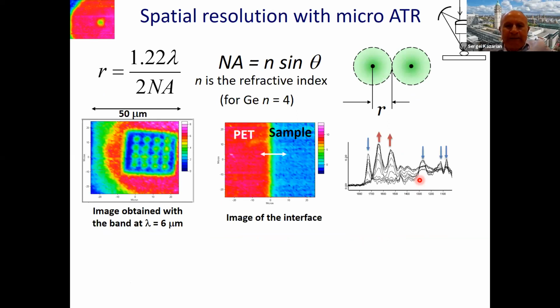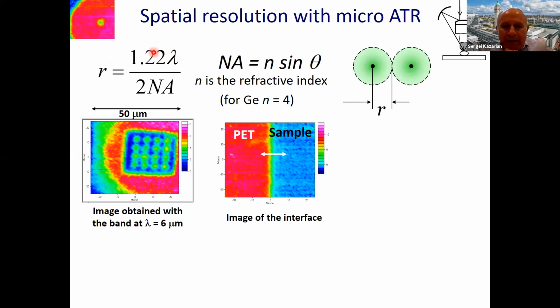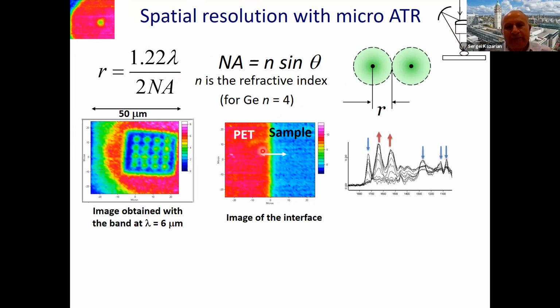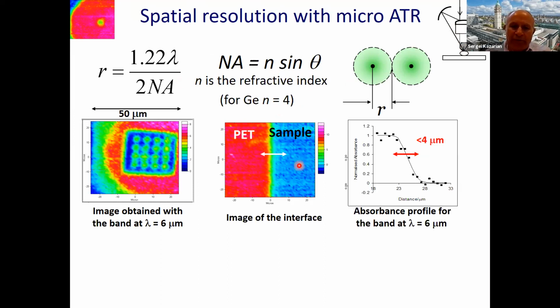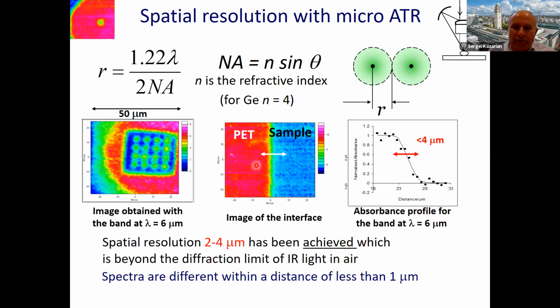This slide is quite complex, and I would like just to point out that spatial resolution is, of course, defined by the Rayleigh criterion, wavelength of light divided by numerical aperture, and numerical aperture is determined by this angle, half of this angle, and refractive index. So if you take a germanium crystal, here the medium where infrared light passes, refractive index 4, you increase numerical aperture by 4 times, and therefore we can resolve much smaller features. For example, here, as a stringent test, we introduce measuring an interface between 2 different polymers, and then we measure how absorbance decays as a function of pixels here. You can see it's about 4 micrometers. It's important to highlight here that we were using 64 by 64 pixels.